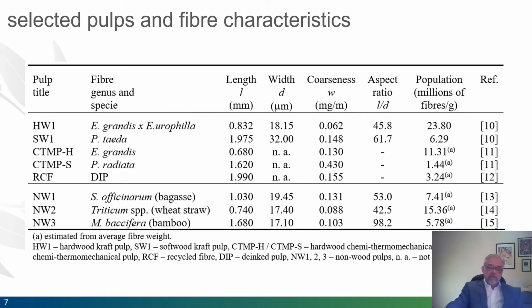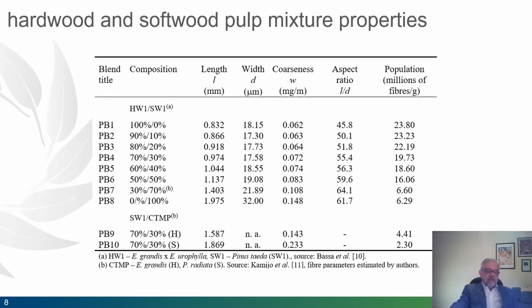Here we can see different hardwood and softwood fiber characteristics, mainly from eucalyptus and pinus species. The table also shows features of recycled fiber represented by deinked pulp and non-wood raw materials like bagasse, wheat straw, and bamboo. The fiber morphological properties of all pulps in the table were used to characterize the different tissue furnishes in terms of crowding number and relative formation indexes. This slide shows fiber properties of blended hardwood and softwood pulps used in the present study. In the table, we can see how fiber length and coarseness vary as a function of the increase of the mass fraction of softwood in the mix with hardwood.